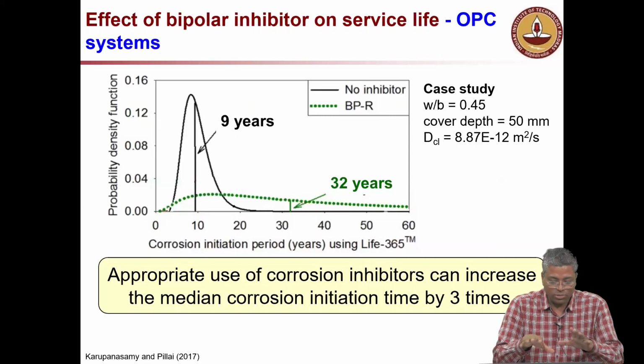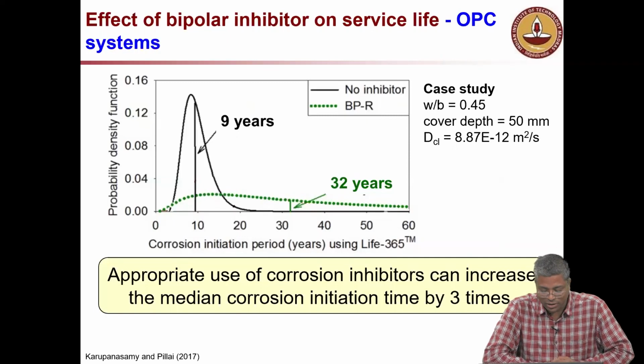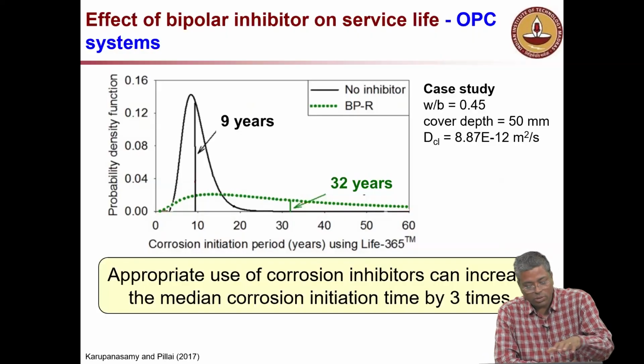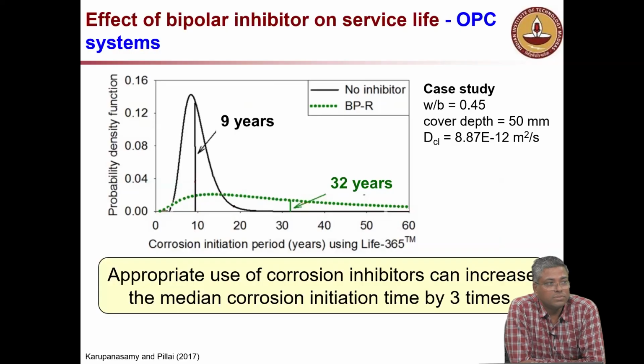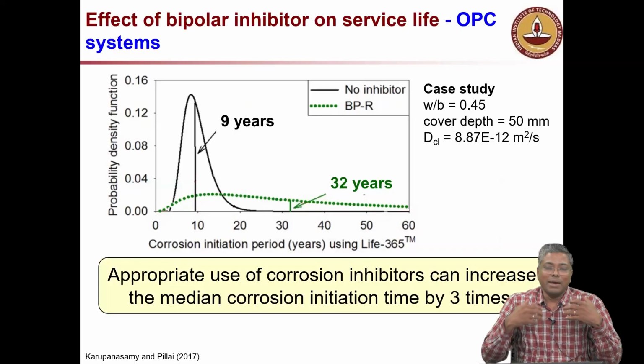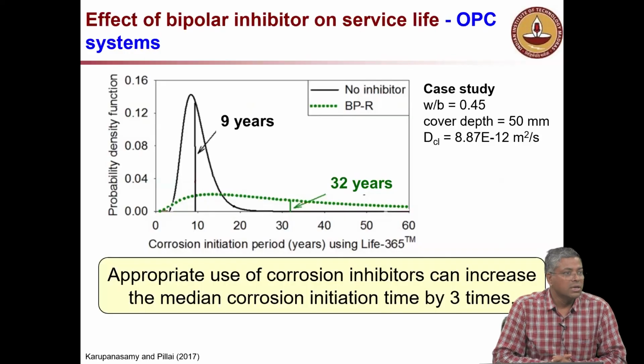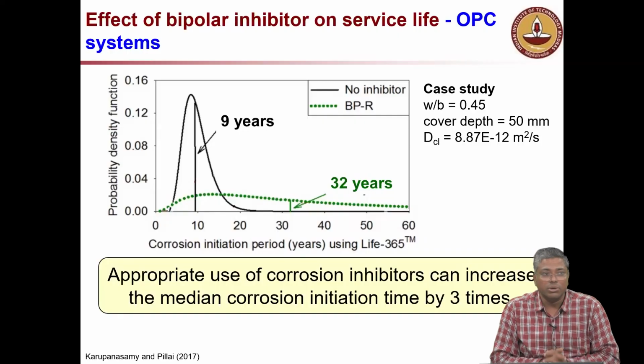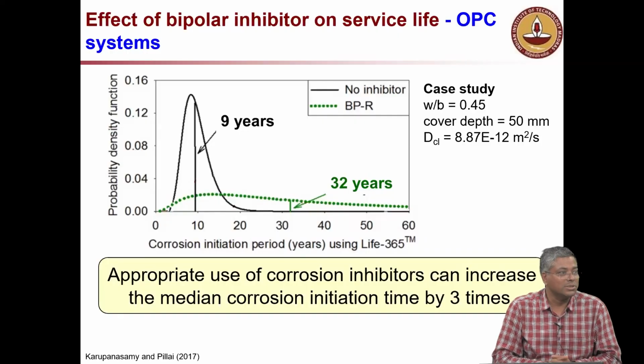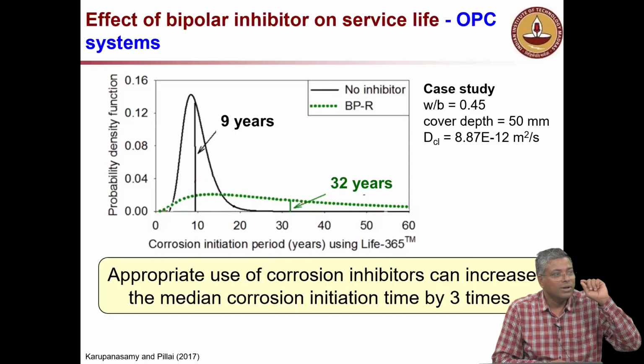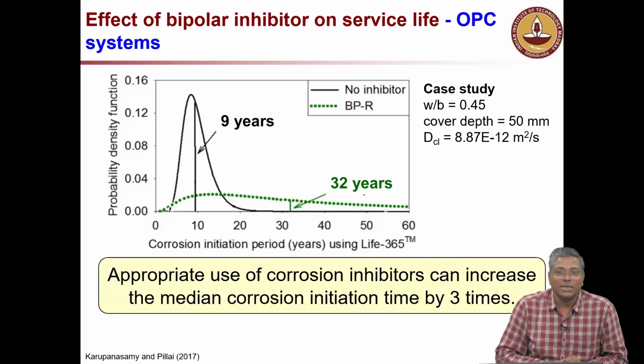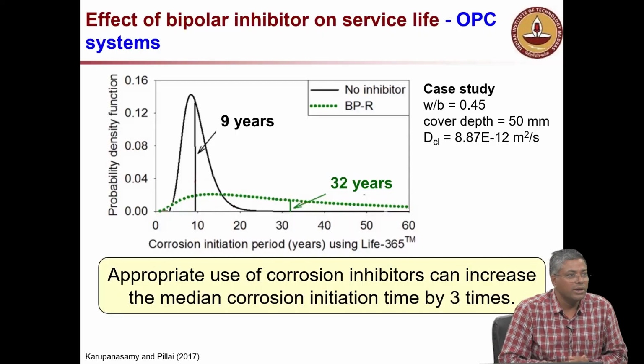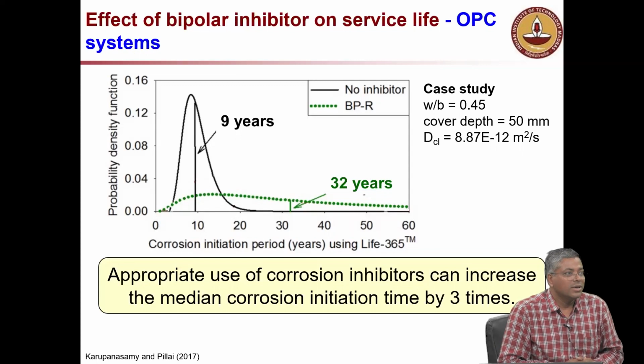Why? So this is a parametric study we did earlier. Jayachandran did it. So you can see almost 3 times increase in the average service life with and without inhibitors. I'm not telling you to take this slide as it is, but what I mean to say is that it is very beneficial to use inhibitors. This is from Jayachandran's PhD. But one problem with this inhibitor, why people don't really use it, is because there is no vested interest on the contractor's side.